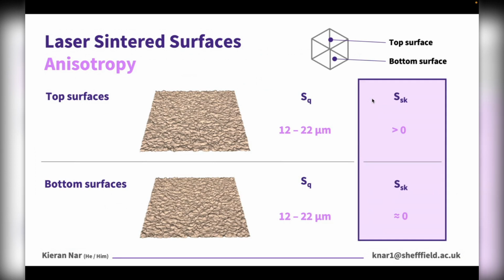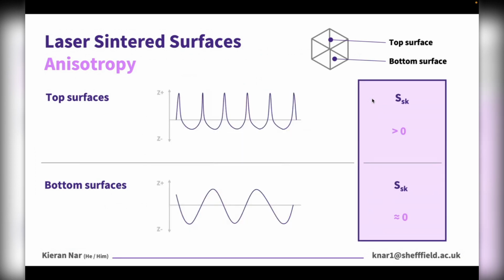But things got interesting when we started to compare their skewness values. So yeah, the one clear and obvious trend that we did manage to see was that the skewness values of top surfaces were almost always positive, so greater than 0, which meant that these resultant top surfaces were asperity peak dominated, whereas the skewness values of bottom surfaces of samples produced typically were centered around 0, which meant that they were relatively Gaussian, and therefore featured neither peaks nor valleys.